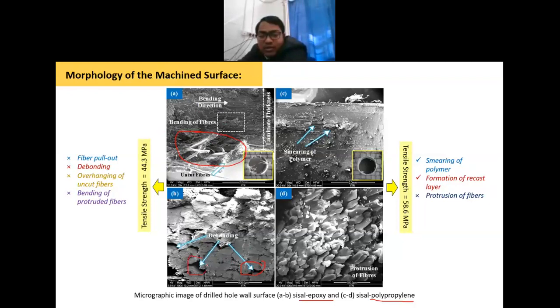So these are the common modes of damage that we observe when machining these materials, like fiber pull out, debonding, overhanging of the fiber, and bending of protruded fibers, when I make a hole in this thermosetting polymer based composite material. But for thermoplastic based composite materials, you can see the amount of damage is comparatively less.